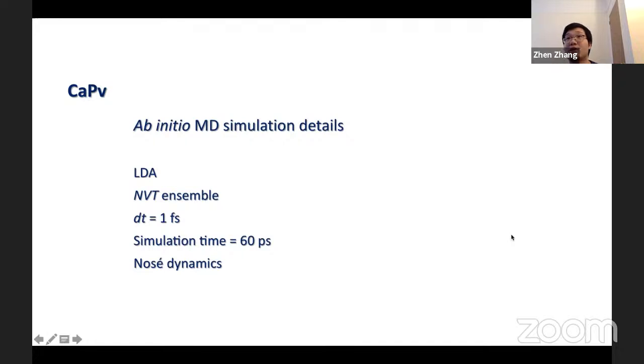Therefore, we carried out ab initio MD simulations for cubic calcium perovskite and applied the phonon quasi-particle approach. LDA was chosen for the exchange correlation functional, and MD was conducted in the NVT ensemble. Each MD ran for over 60 picoseconds with a time step of 1 femtosecond. Temperature was controlled through the Nosé dynamics.